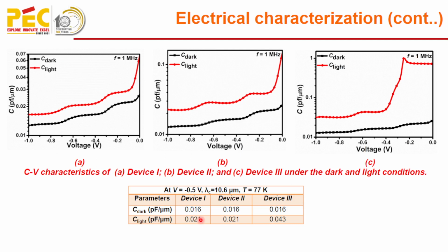Now I have also plotted the photo switching response of all the devices under 1 watt per meter square light intensity at the wavelength of 10.6 micrometer at a temperature of 77 Kelvin. The IR radiation was switched on and off for 10 seconds and the photocurrent was recorded. From the figure it is clear that device 1 and device 2 show persistent slow switching, meaning they show a slow exponential rise and decay of the current under IR illumination and dark condition, whereas device 3 shows a quick, rapid, or sharp switching photo response.